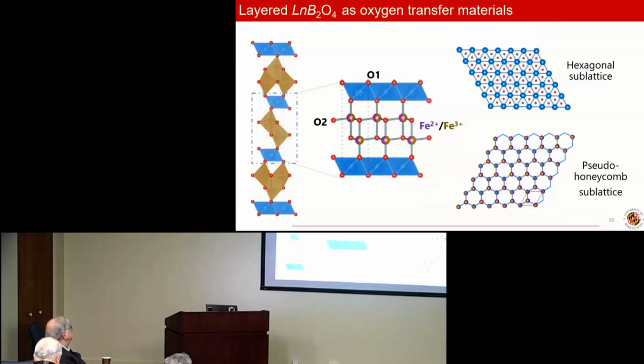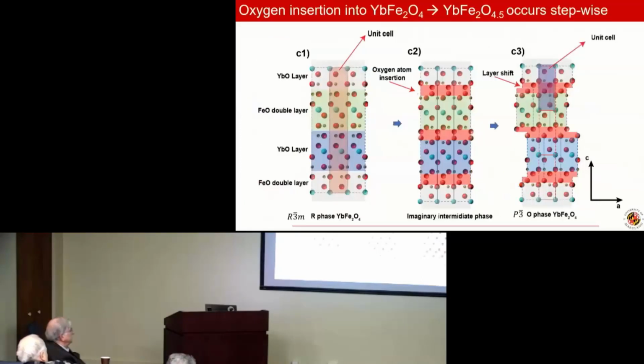What we've been looking at more recently are not perovskites necessarily, but these 1,2,4 type structures where you have a rare earth or lanthanide. These have been looked at also for multiferroic applications, but we also saw that they're very interesting for doing oxygen insertion. They consist of a hexagonal sublattice with a pseudo honeycomb sublattice in the transition metal site. I say pseudo because it's kind of like a corrugated honeycomb. It's not a flat honeycomb. What these materials are good at, and this is just a cartoon image of what happens, is they readily take off oxygen, and due to Coulombic repulsion interactions, the layers just slip past one another. So it goes from a rhombohedral to a trigonal space group, and we wanted to understand how that happens. It's a fairly complex crystallographic transition.